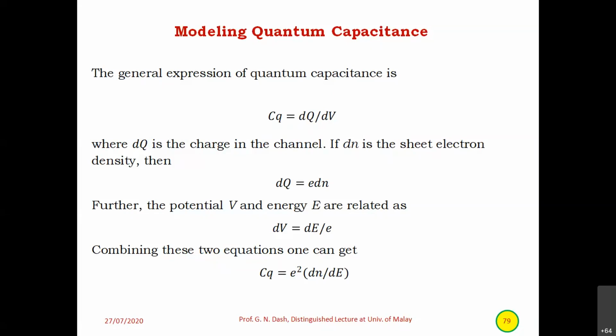in two-dimensional materials, the charge is continuously distributed from top plate to bottom plate. Whereas in classical capacitors, the charges reside only on the top plate and bottom plate, and in between there is no charge. So that makes the difference of quantum capacitance. Here dq is the charge in the channel. If dn is the sheet electron density, then dq is equal to q into dn, and dV is equal to dE by q. If you combine these two, you get quantum capacitance equal to q square into dn by dE, that means the rate of change of electron density with respect to energy.